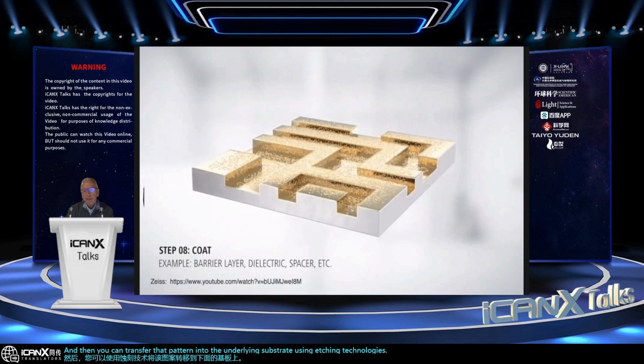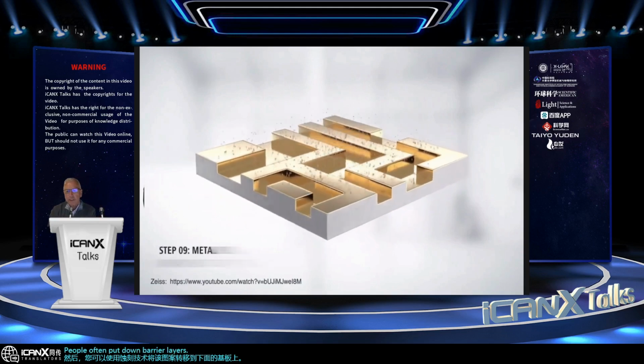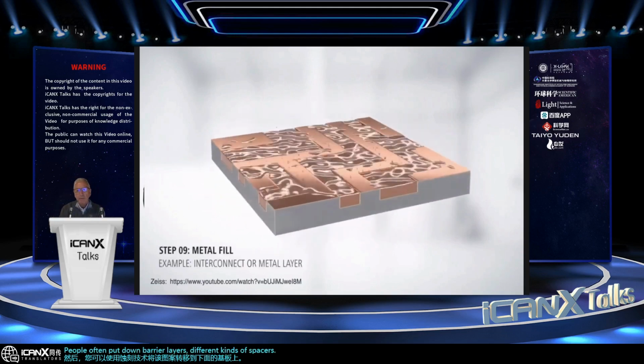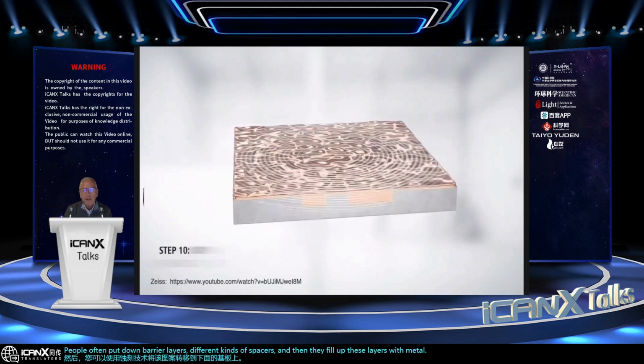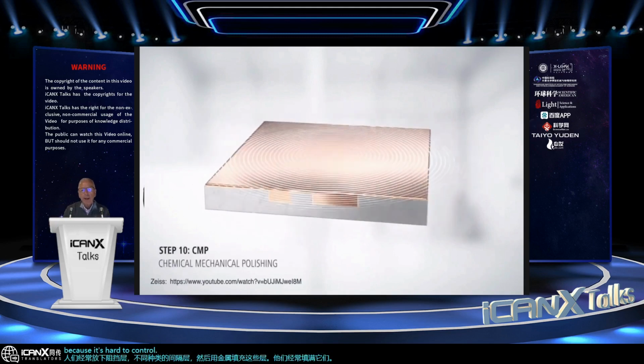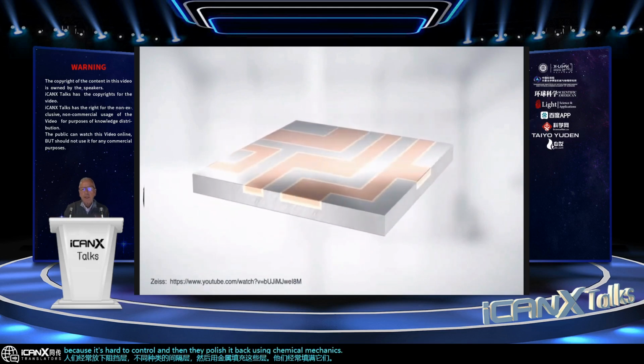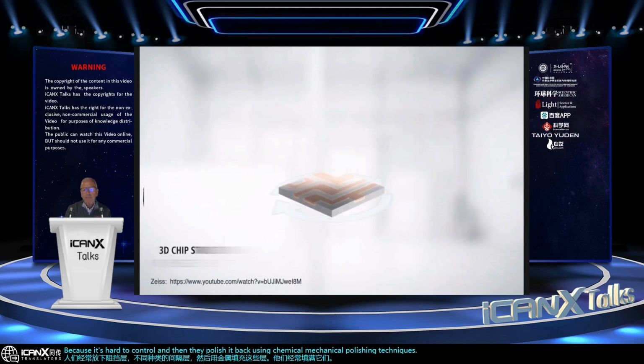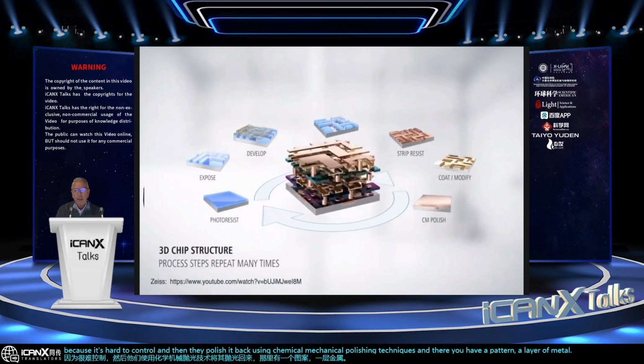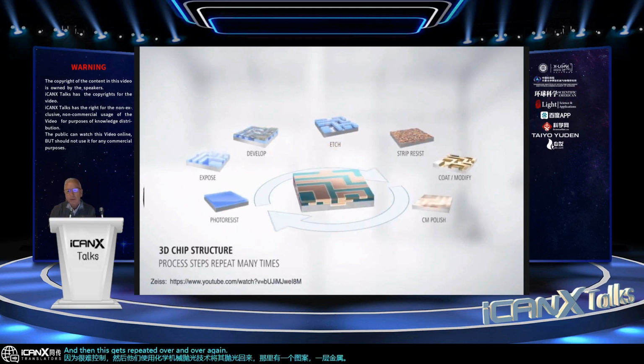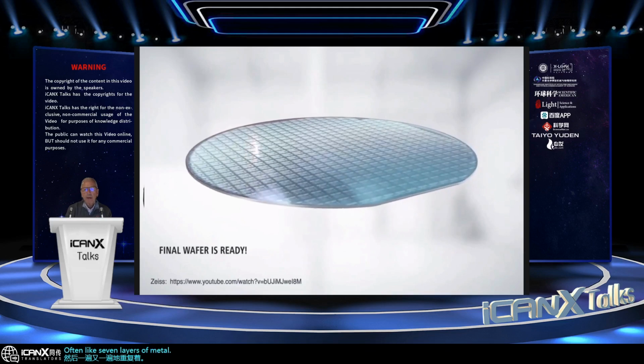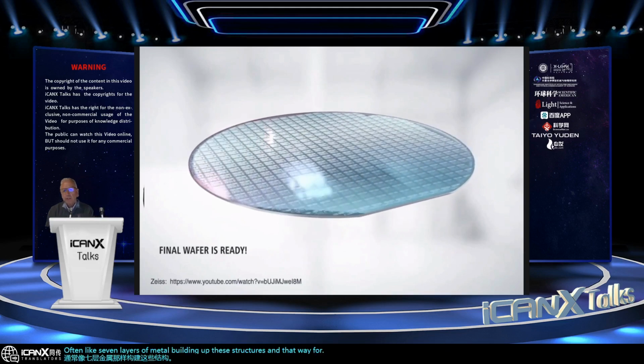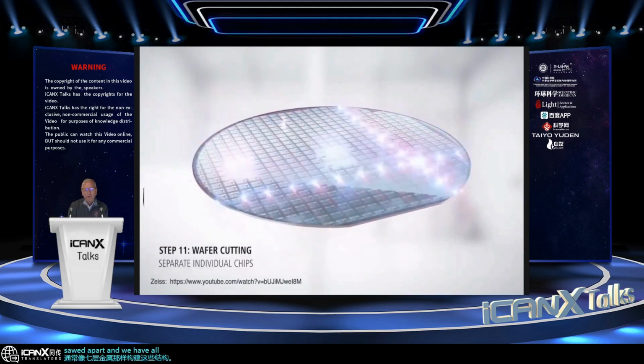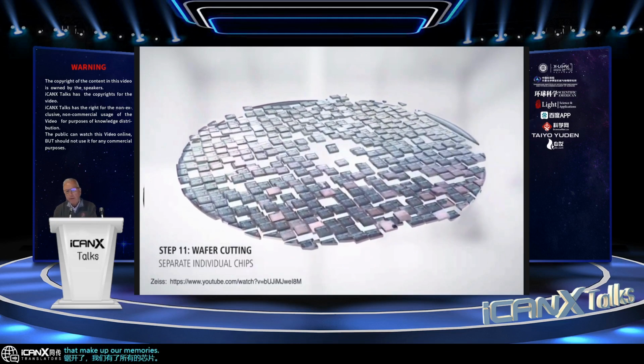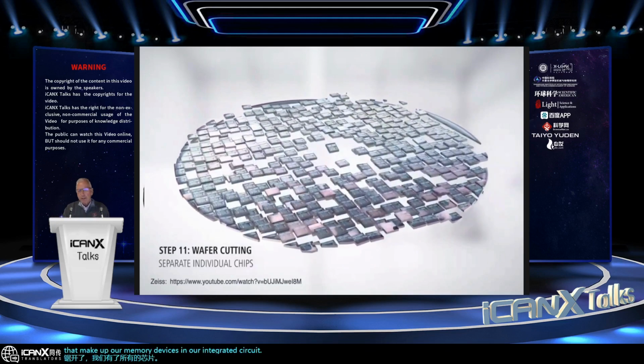People often put down barrier layers, different kinds of spacers, and then they fill up these layers with metal. They often overfill them because it's hard to control, and then they polish it back using chemical mechanical polishing techniques. And there you have a pattern, a layer of metal. And then this gets repeated over and over again, and there's often like 7 layers of metal building up these structures, and then that wafer gets sawed apart, and we have all the individual chips that make up our memory devices and our integrated circuits. So that's the microelectronics industry in a nutshell.